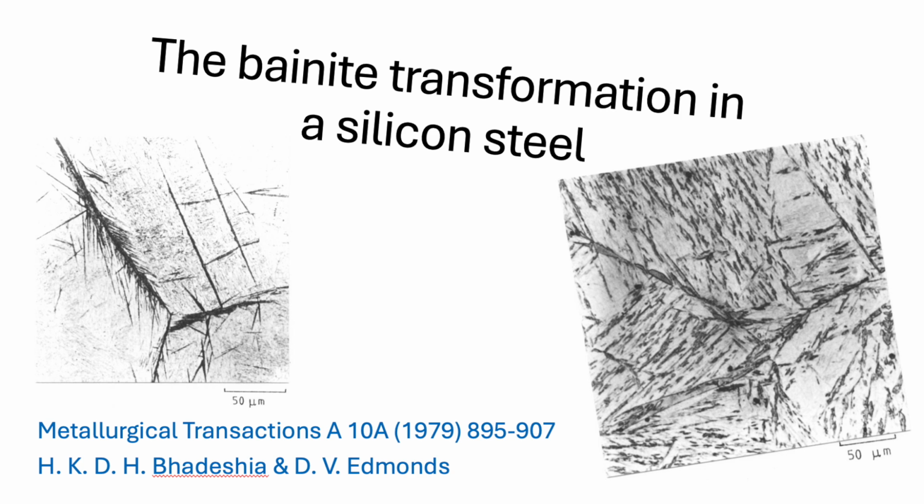It's considered really strong metallographic evidence for the idea that bainite grows by the repeated formation of small, discrete displacive shear units. So not a continuous, smooth growth front. No. It suggests the interface advances stepwise. A 0.2 micron unit shears, transforms, then another one nucleates right next to it or at its tip and shears and so on, like little building blocks snapping into place via shear. Repeated nucleation and shear of subunits, that's a fundamentally discontinuous growth mechanism. Exactly. It's the visual confirmation of the shear model operating on a very fine scale.